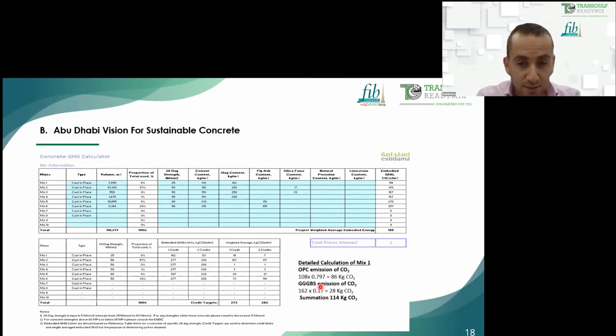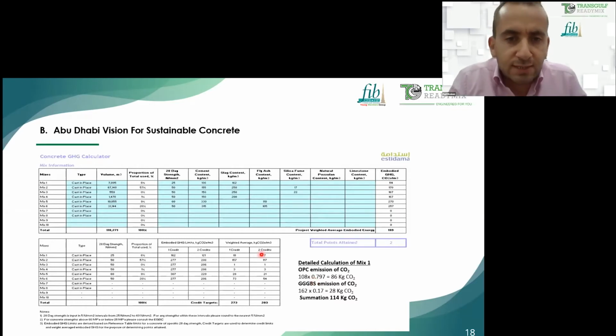As you can see, the mass is much higher, and the amount of CO2 emission is much less than OPC. So it will make a difference using the supplementary cementitious material. As we can see here, if we add both, 86 and 28, we will get a total of 114 kg.